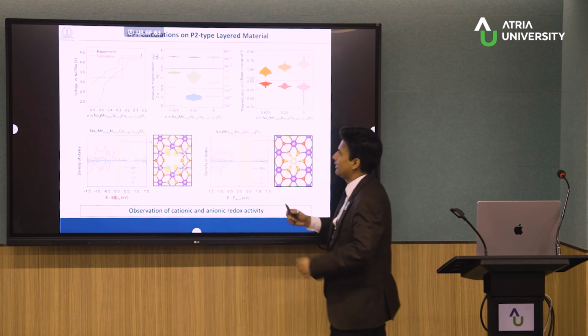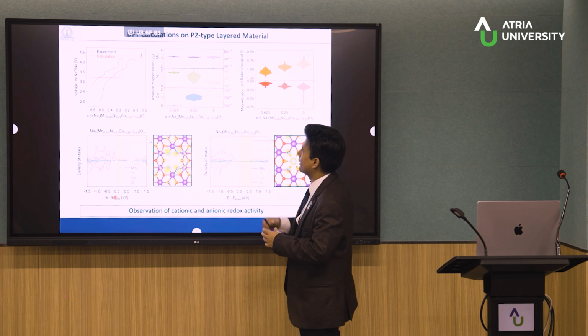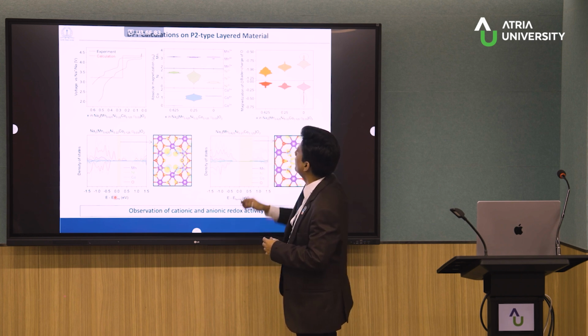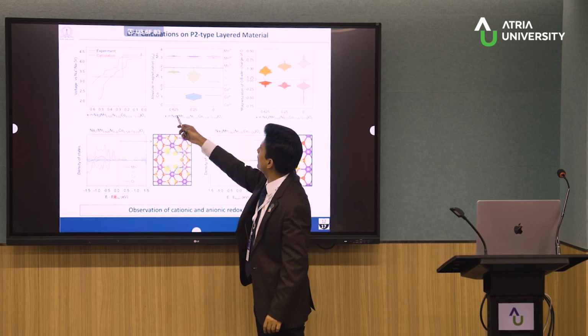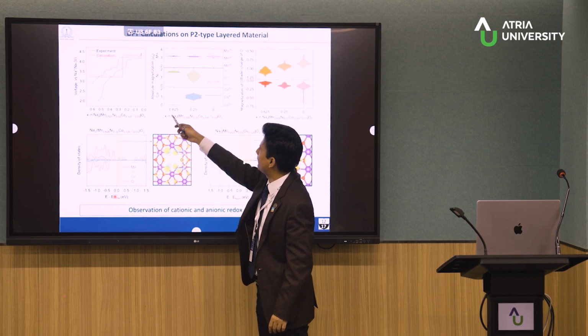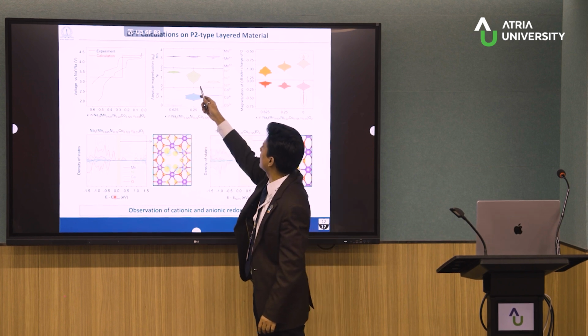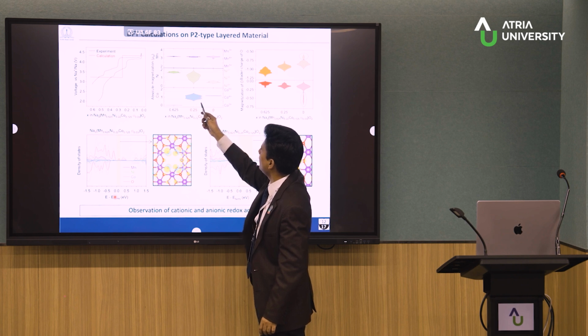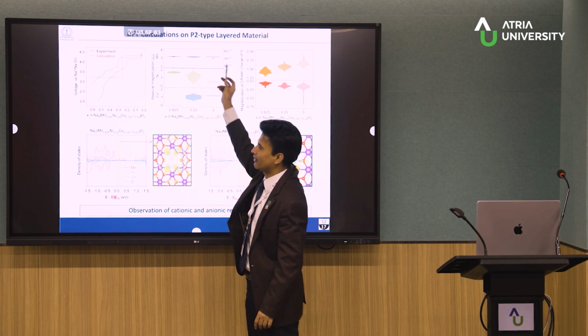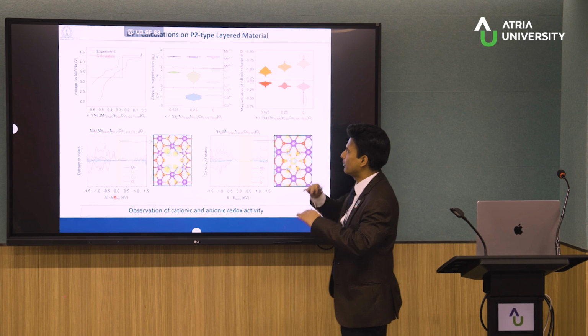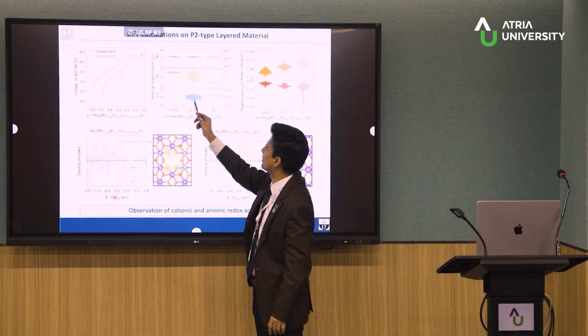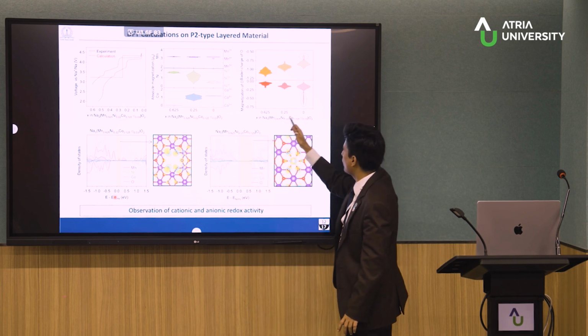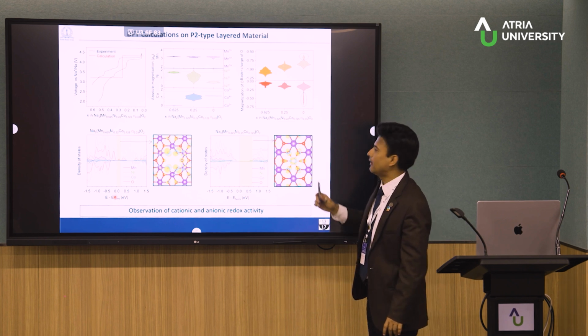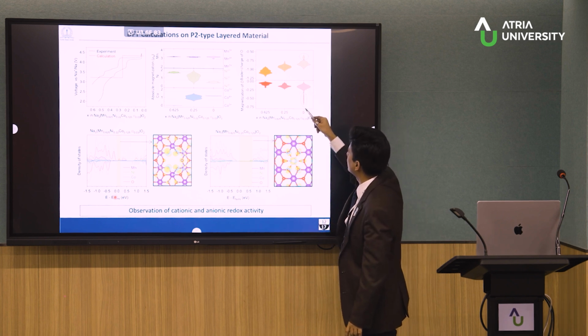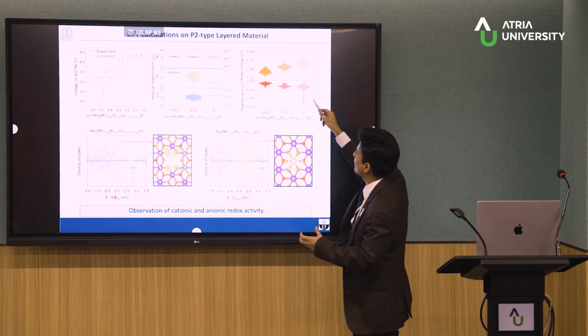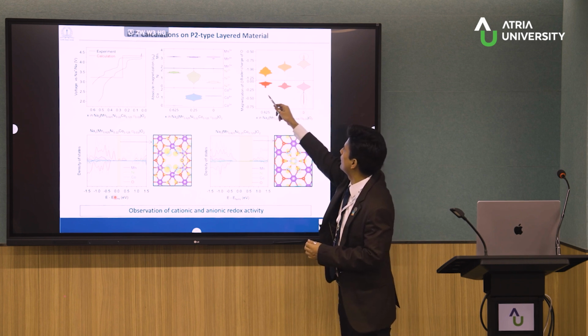And when they did the Bader charge calculation and the transition metal charge calculation, they can see we are indeed getting the nickel redox at a different degree of sodiation. The nickel is active and cobalt redox is happening, and the manganese doesn't change much. Yeah? So the manganese is the same. Most of the activity is coming because of nickel and some amount from cobalt. And when we go to high degree of desodiation, indeed they can see oxygen redox is coming. Yeah? This is all because of the Bader charge of oxygen, and you can see it is seriously changing.